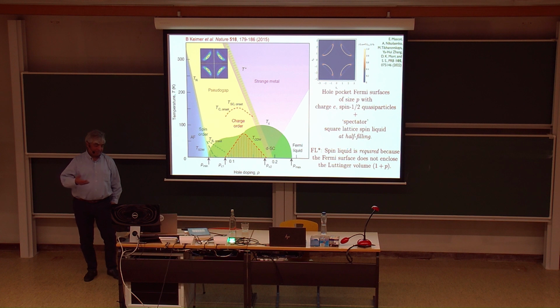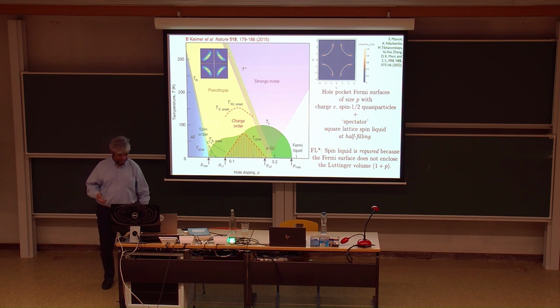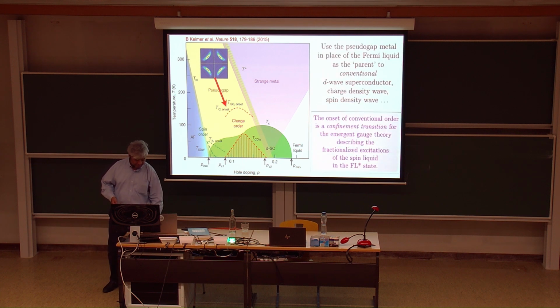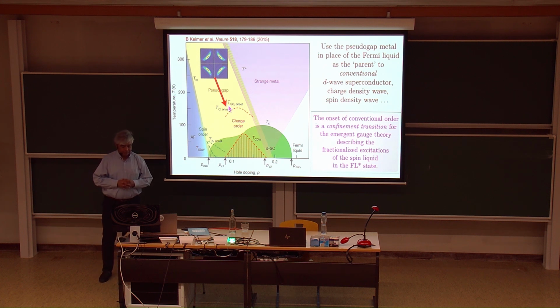And this spin liquid will play a crucial role in this low temperature instability. So this is the summary of my talk, if I don't get to it. The onset of conventional order, meaning order to superconductivity or charge density wave or spin density wave, is a confinement transition of an emergent gauge theory. You have to use an emergent gauge theory to describe the spin liquid.